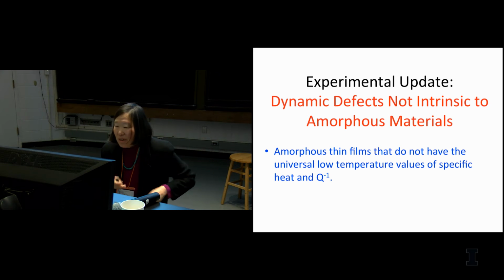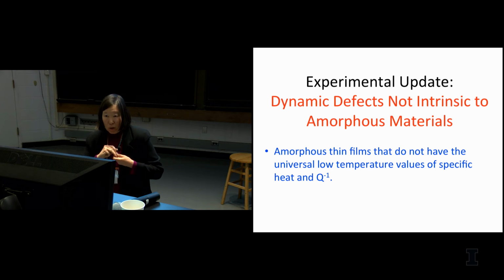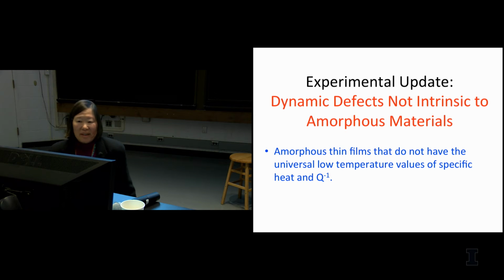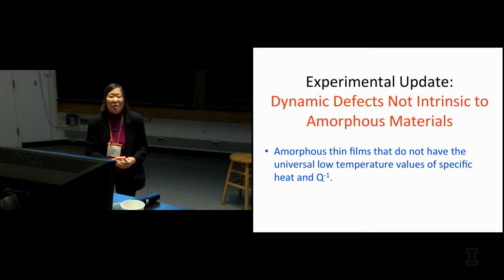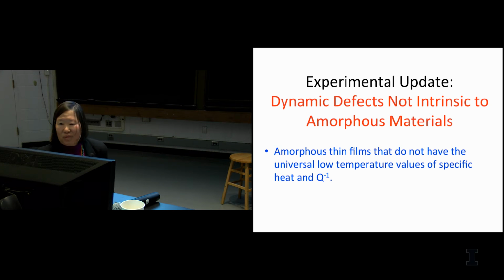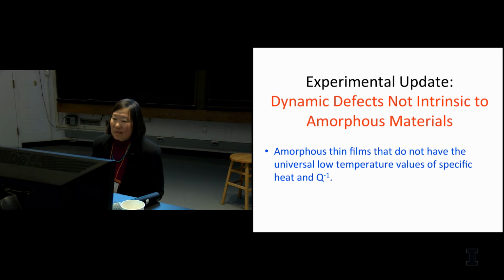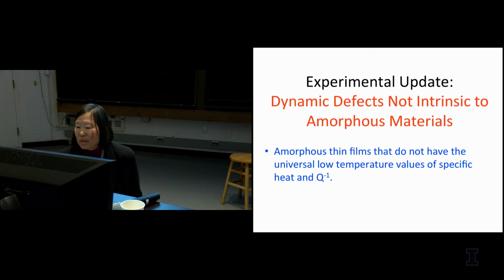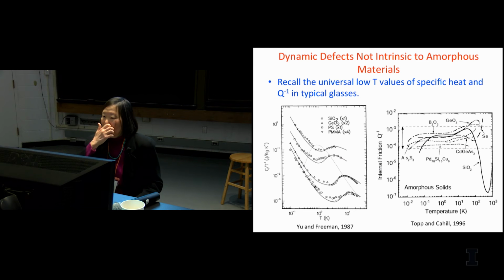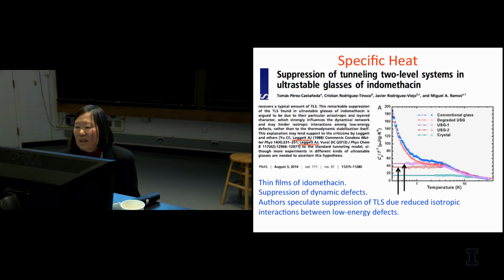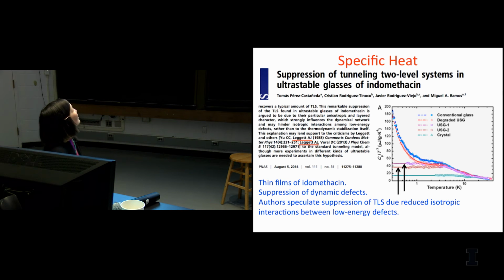Okay, so let me just give a quick experimental update on some things that have happened since then. The message here is that the defects, I guess we shouldn't call them two-level systems, but Tony likes to call them non-phononic degrees of freedom. These defects are not intrinsic to amorphous materials. I'm going to show you an experiment showing that thin films, which are amorphous, don't have these low-energy defects. So perhaps this is the exception that proves the rule, which is a saying Tony often likes to say.